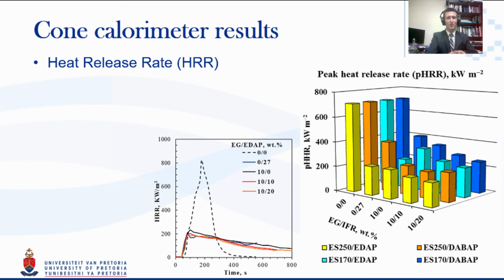Now, this actually shows it quite a bit better. So what you'll see here is that each of these lines represent one of our mixtures. ES250 is the low temperature. So the first two on the right are the low temperature expandable graphite mixed with EDAP and DABAP respectively, whereas the rear two are for the higher onset temperature material.